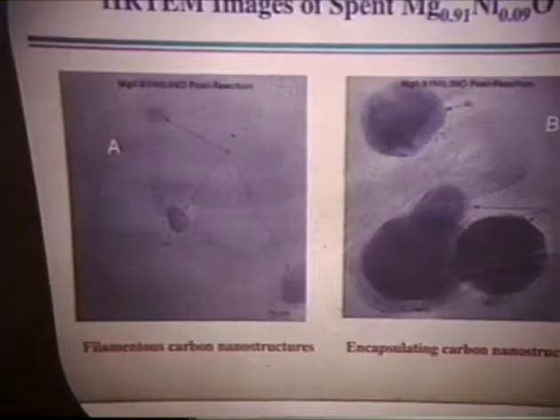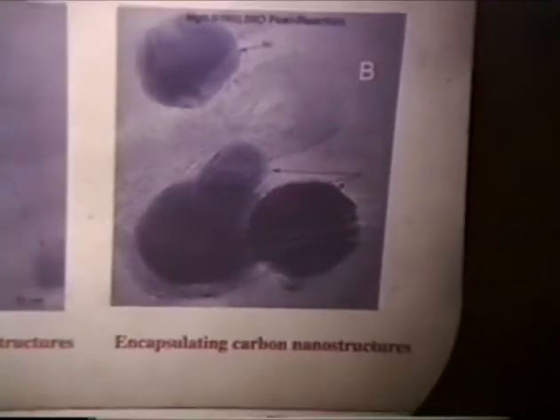With the promoter there, with the manganese, you no longer can see these nickel particles sweating out of the MgO solution. It all looks relatively even, and you can't really see much carbon either. If you find a little carbon nanoloop, you can't really associate it with the nickel particle, per se. Whereas with the other catalysts that we saw earlier, if you look carefully, you can see turbostratic carbon building up around the nickel particles. And, of course, you can quantify that carbon by TGA.